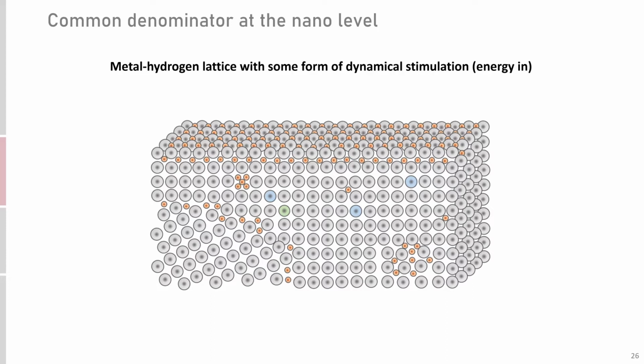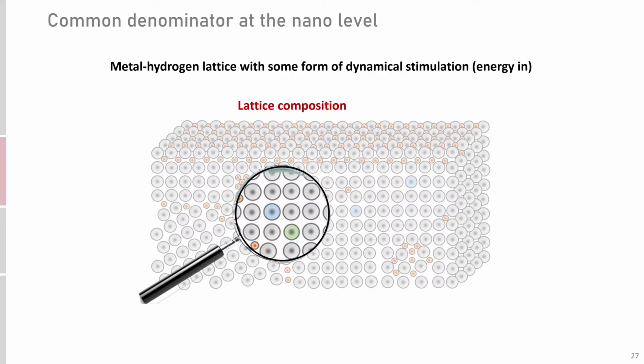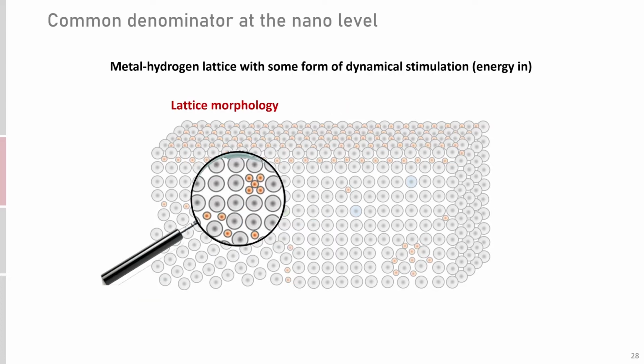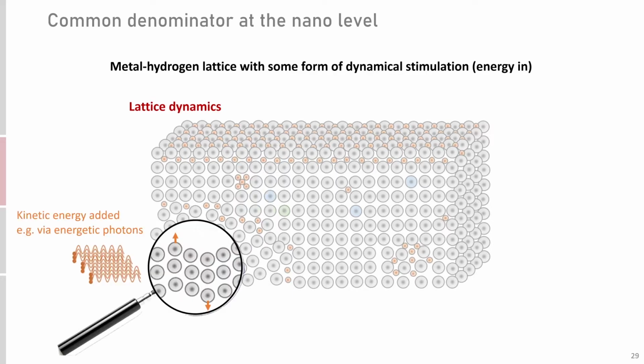And this is, in the most general terms, what we can find at the nano level in all of these systems. We have a metal lattice with some hydrogen atoms loaded into parts of it, but the lattice is likely not homogeneous. There are impurities in it, maybe alloying components. So we have to consider the lattice composition. And then there are defects in the lattice, such as vacancies, cracks, and grain boundaries. So we have to consider the lattice morphology.